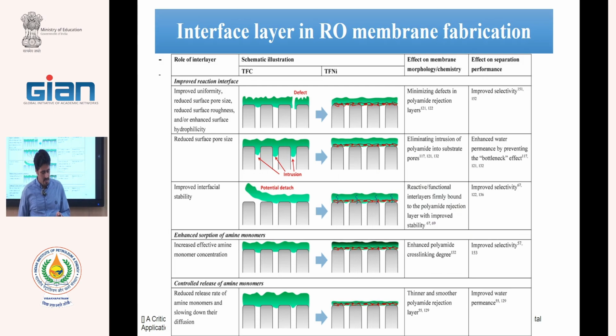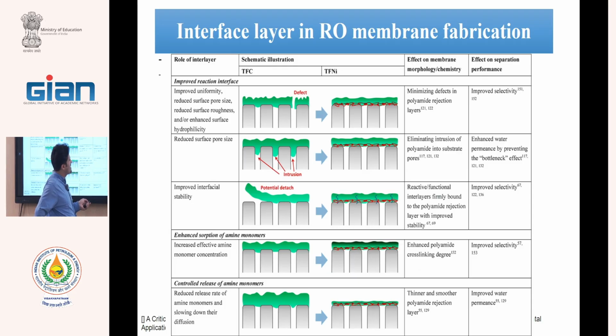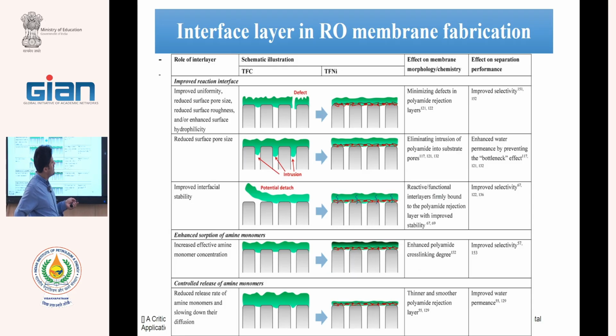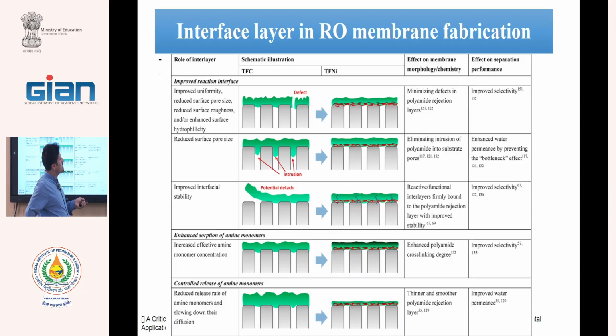This slide compare and show the effect of this thin interface layer. Say that the use of, for example here, for use of this interface layer, increase the stability, can act as an attachment, as an adhesive, and increase the attachment of this layer. Or this interface layer do not permit for intrusion of the polyamide layer in pores and reduce the thickness. This have lower thickness than and increase the flux. Okay, and other properties. Therefore, in recent published RO membranes, the use of interface layer is very important.